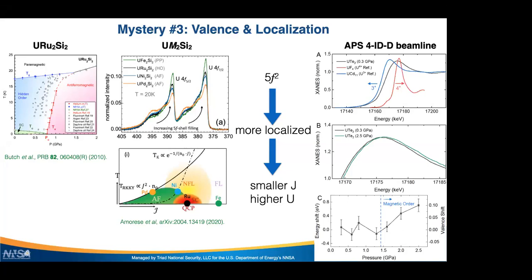And here you can see the L3 edge of uranium and the XANES spectra compared to UCd11, which is a good 3+ reference, and UF4, which is a good 4+ reference. So the XANES spectrum of UTe2 is somewhere in the middle. So we don't have a really 3+, nor a 4+ configuration, but it is closer to a 4+ configuration. So we can think that we have a mostly 5f2 configuration with a little bit of 5f3.